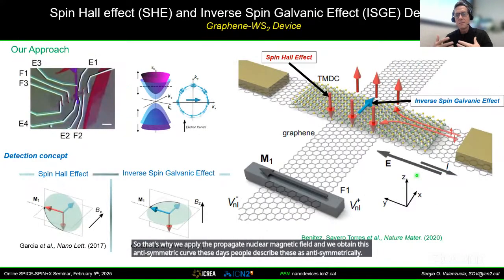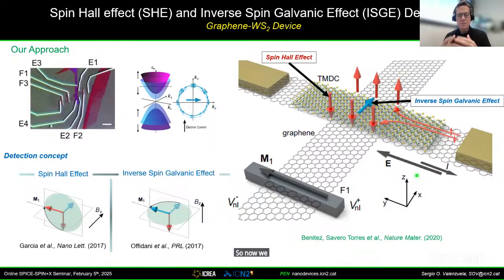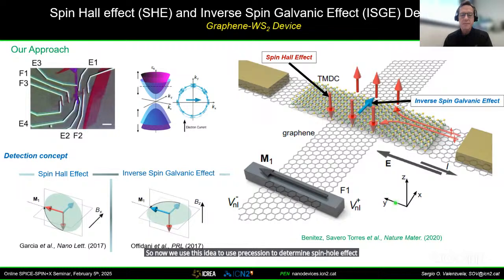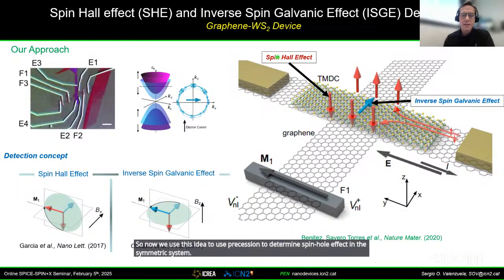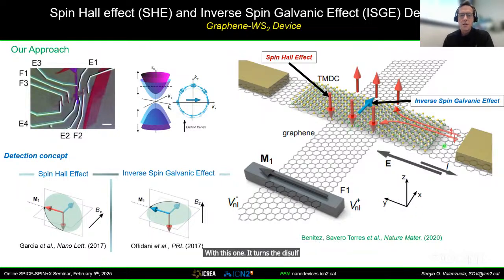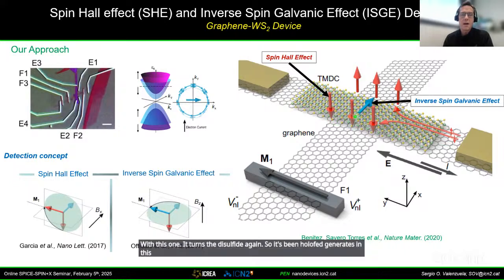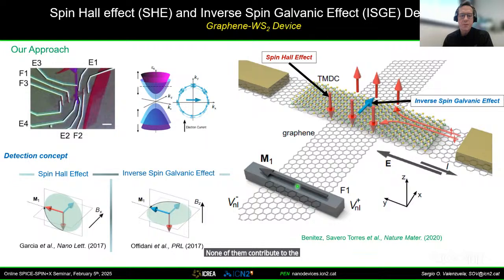So now we use this idea to use precession to determine spin Hall effect in the symmetric system. With this one, the tungsten disulfide again. So a spin Hall effect generates in this structure spins that are out of plane, as shown here, and the inverse spin galvanic effect generates by proximity spins that are oriented in plane. None of them contribute to the signal at zero magnetic field if they are perpendicular to the ferromagnet magnetization.